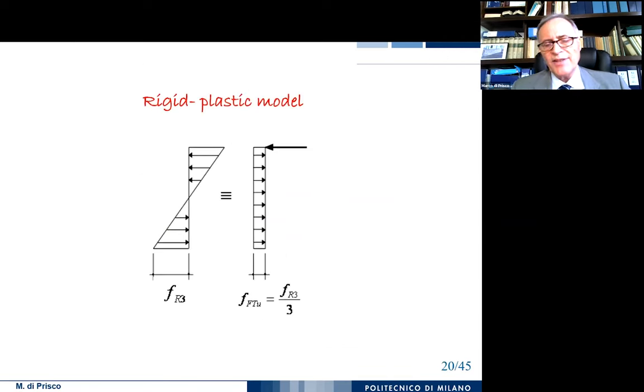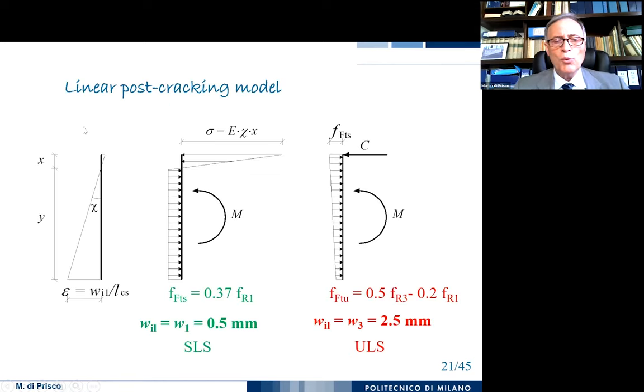Now, in order to correlate the constitutive law in uniaxial tension to the residual bending strengths, which are nominal, of course, we can essentially produce, for the rigid plastic model, an equivalence in terms of bending moment between these two idealizations of distribution of stresses along the cross section. And for the linear model, we need to assume the linear strain behavior on the cross section. And then, as usual, for the serviceability we have three unknowns: the stress on the top in the compressed concrete, and the FFTS, which corresponds to a sort of elastoplastic behavior for the serviceability region. Then we can use also rotational equilibrium and translational equilibrium, and we arrive to define this value.